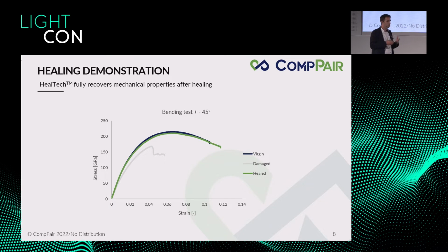So we need also some specific testing to show real-life conditions, and a static test in a lab is not really representative of what will happen into real life. And so here, this test shows bending on a specific layer where you damage the matrix specifically for a virgin material, so without any damage. For a damaged material, you see that the mechanical properties are reduced, and for a damaged and healed one, you see that we recover the mechanical properties.